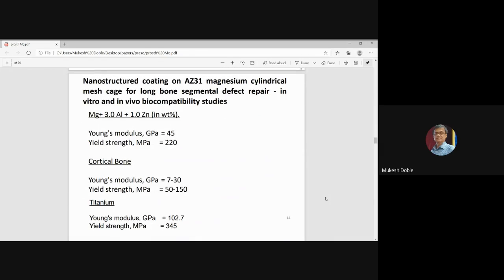So like I mentioned, titanium has very high Young's modulus, high yield strength. So we looked at a magnesium-based material, magnesium alloy AZ31. This is magnesium with aluminum 3% and 1% zinc by weight. Look at this, Young's modulus is 45, although it's not at bone level, it's much lower than titanium. It's slowly coming towards bone. Yield strength is 220 when compared to titanium, which is 345. So there is nowadays a lot of interest in magnesium-based alloys, because magnesium has good properties and more towards bone when compared to stainless steel or titanium, which have mechanical properties far away from bone.